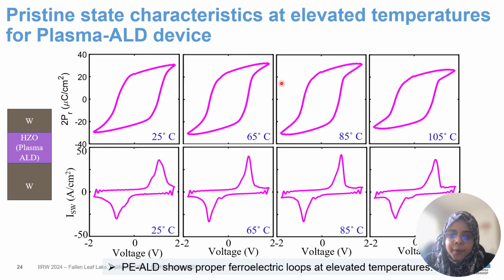It tells us that even at higher temperature, till 105 or 125 degrees Celsius, the plasma ALD device is able to maintain its wake-up free behavior, and it doesn't need any wake-up cycles, or any cycling, to get proper hysteresis and proper ferroelectric switching, because we're already having it in our pristine state.